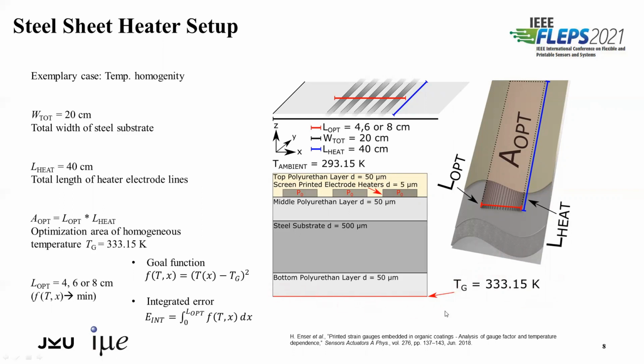The red optimization length L_opt is the length along the substrate where the optimization algorithm optimizes for this temperature distribution by changing the distances between these electrodes here. And we therefore have a goal function f from T and x, which should be minimized for each point x, where x is the position along L_opt. And the total integrated error is defined as the line integral of the goal function over the optimization length, so that the final optimized temperature distribution has a minimal integrated error.